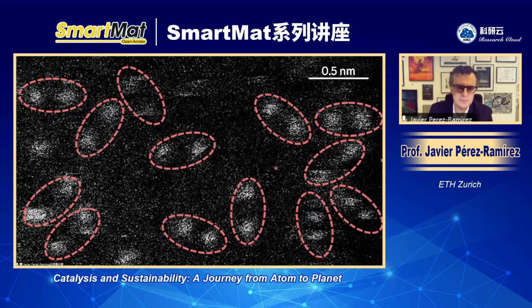Now, these geminal sites can be visualized. You can see this very beautiful micrograph where you see the pairs of copper sites, stabilized on the structure of polymeric carbon nitride. And what these pairs of copper could afford is actually doing reactions that will be completely impossible to do if these copper atoms will be completely isolated. That means a classical single atom catalyst, where there will be no neighboring copper site, just one copper atom completely isolated compared to these twins, these pairs of copper sites. These copper sites in pair form, as I said, they generate unique reactivity.